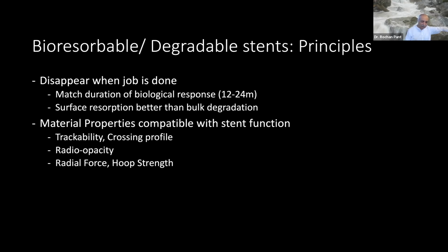The other part, the resorption should not happen in a patchy manner. It should happen globally. You can't have one strut of the scaffold suddenly being reabsorbed and other part of the thing still remains. That will degrade its mechanical properties and might lose function early. And this is a problem which did happen with some materials which were tried. Okay? So slow surface resorption is better than bulk degradation of the material that the scaffold is made of. And very importantly and more difficult, material properties should be compatible with stent function. That means it should match at least the currently existing metallic stents in terms of trackability, crossing profile, radio opacity, radial force, hoop strength, and all the things we spoke about.